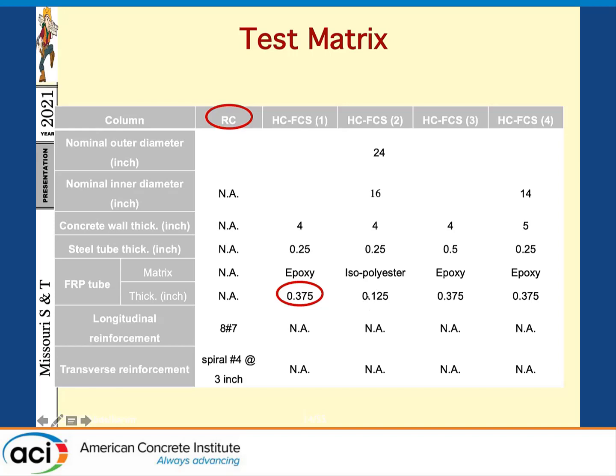thick tube. The other parameter that we looked at is the thickness of the steel tube. Again, the common is 1/4 inch, but we also tested one with 1/2 inch. For concrete wall thickness, the common is 4 inch, and one was tested with 5 inch. One of the parameters, when you are talking about the cost of the FRP tubes, is that the common resin for the tube itself was epoxy, but for one of the columns we used isopolyester in order to try to reduce the cost. Isopolyester is much cheaper than epoxy resin.